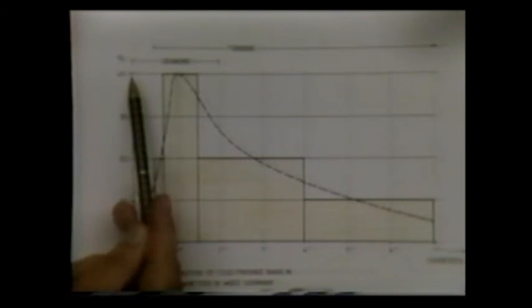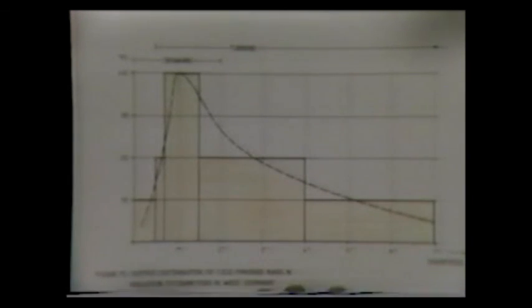This distribution can be taken as typical. You see here the diameters, and here the percentile distribution of the cold finished bars in Germany. This means drawn bright steel is manufactured up to approximately 2-inch, but mainly up to 1¼ or 1½ inch, while turned products start at 1/2 inch and go up to 7-inch and more.